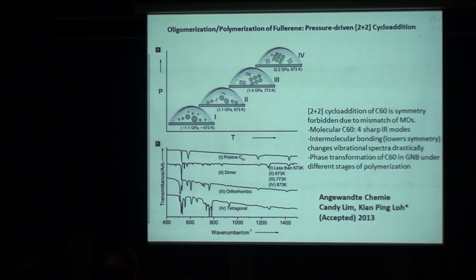To prove this further, we can put in fullerene molecules, C60. It's well known in chemistry that if you want two C60 molecules to bond, intermolecular bonding, the soccer balls are so stable that they don't like to form bonds. This intermolecular bonding between C60 is symmetry forbidden in chemistry. We call this the 2+2 cycloaddition of C60, symmetry forbidden due to the mismatch of molecular orbitals. However, under the high pressure regime, this rule does not apply. Most of the chemistry rules are derived at normal, atmospheric conditions. Under the high pressure regime, you force the molecules to come very close. They have no choice but to form bonds. And when they form bonds, the C60 molecules will polymerize. From two C60 coming together, they form a dimer, a trimer, a tetramer.